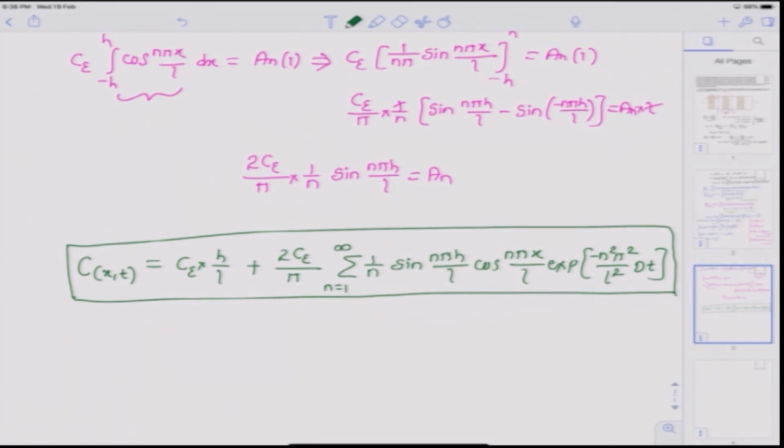Okay. So, this is how we can work with the periodic boundary conditions and solve the diffusion equation using first separation of variable and then using the series expansion. Again, we dealt here with the austenitization problem, which actually is a multi-phase problem. The concentration profile will be a little bit different because of the discontinuity at the interface at all times. As long as the interface is there between two phases, there should be a discontinuity in the concentration profile.